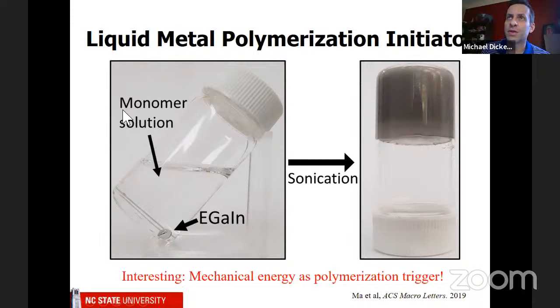Usually, to get polymers to form, you have to use heat or light, and you have to use a special molecule called an initiator that will cause the polymerization to proceed. Here, we don't have any of those things. There's no light, there's no heat, there's no initiator, and we simply sonicate it. And when we're done, we flip it over, and you can see it's turned into a gel. So this is really exciting because it suggests that you could use mechanical energy, just vibrations, to cause chemical reactions.